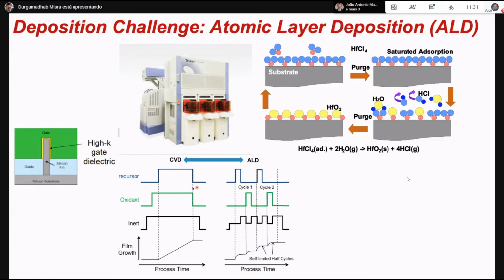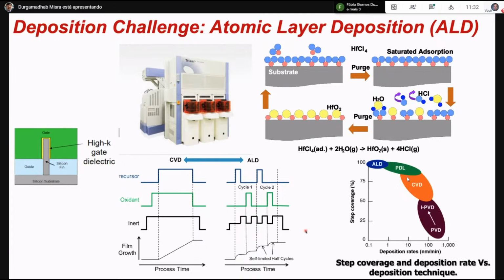But in ALD, you send the precursors in cycles, and then you have oxidants also in a cycle, and then inert gas in a cycle. So depending on cycle 1, cycle 2, like this, you can deposit the dielectric on the top. It does a similar process as in CVD, but it is deposited in a cyclic process. The advantage it has is the step coverage. Normally if you do deposition by CVD, you will not be able to deposit a film of uniform thickness on top of this silicon, but ALD actually improved that to 100% step coverage.